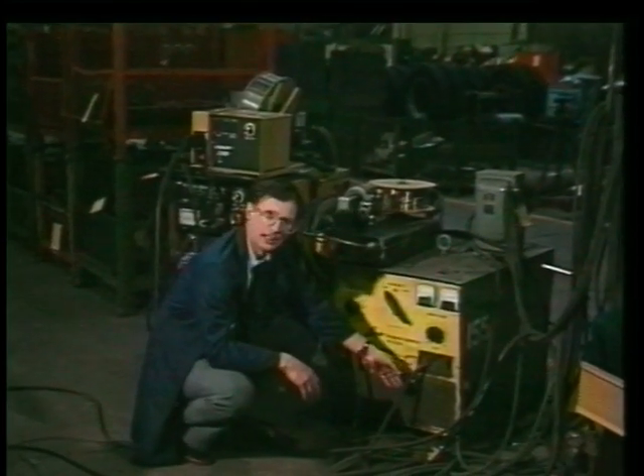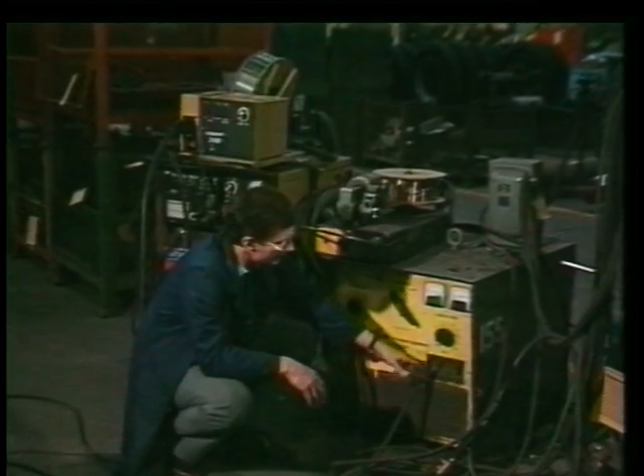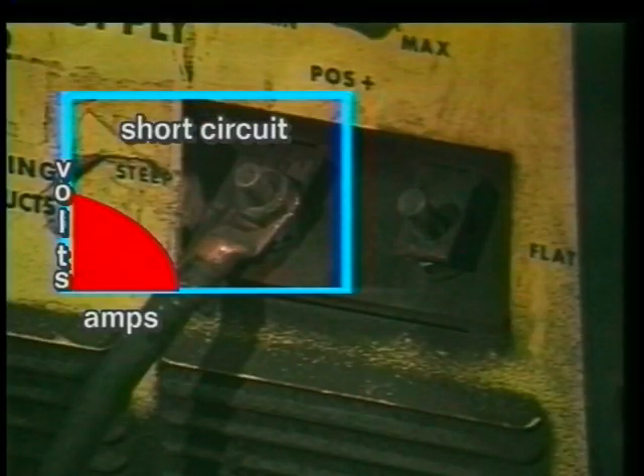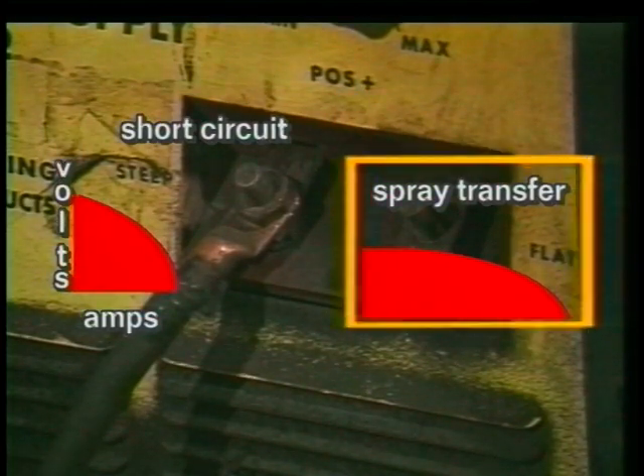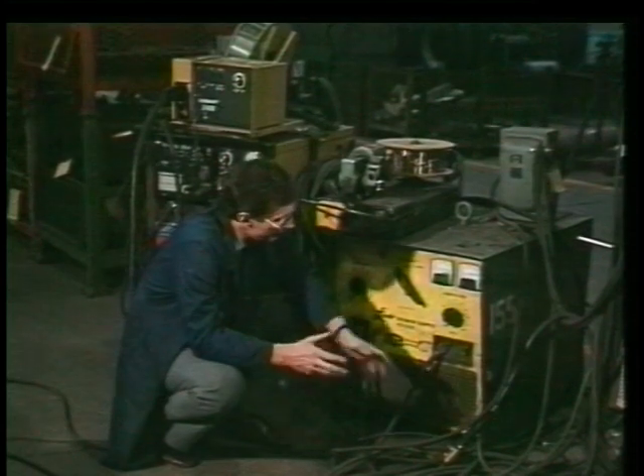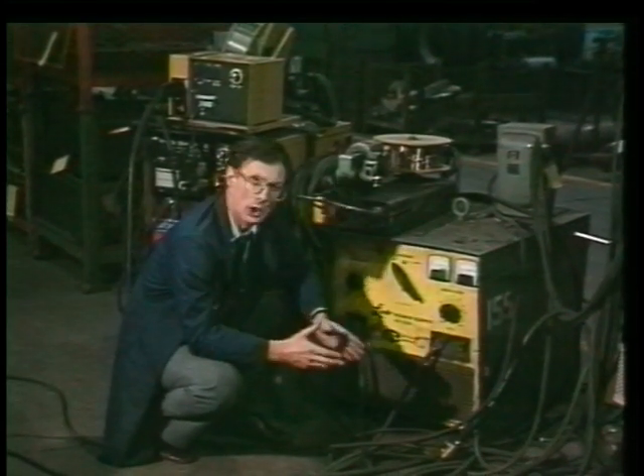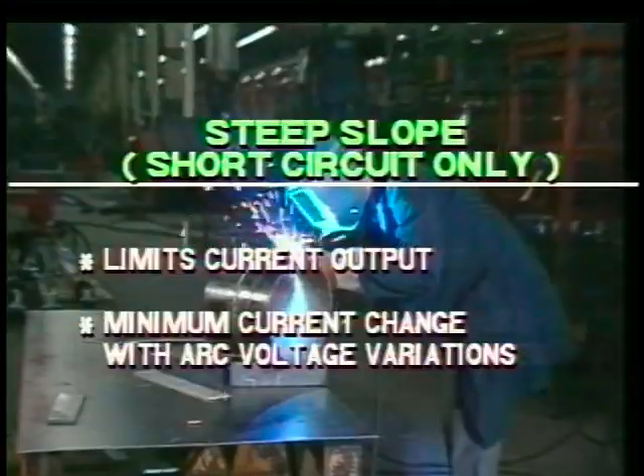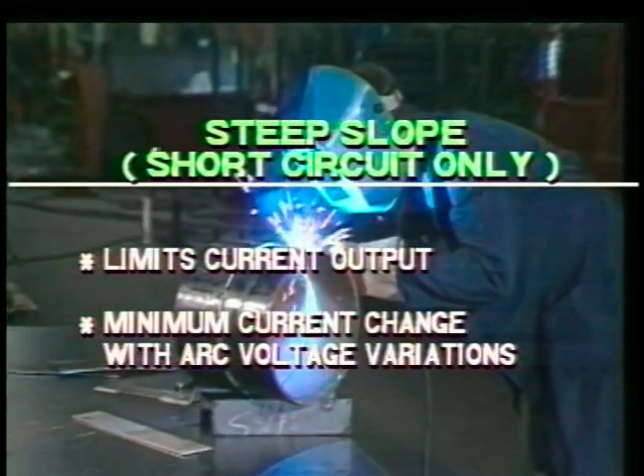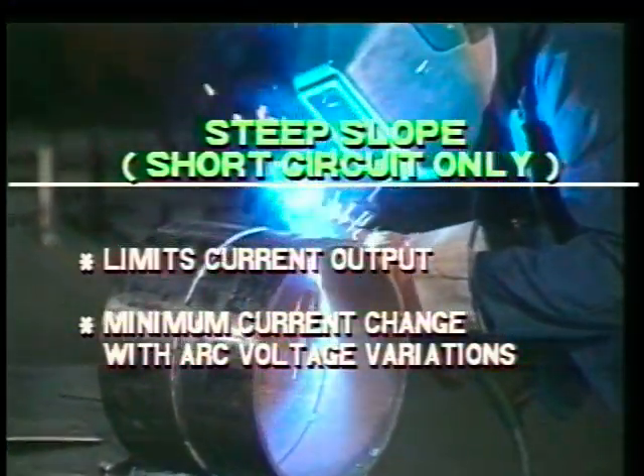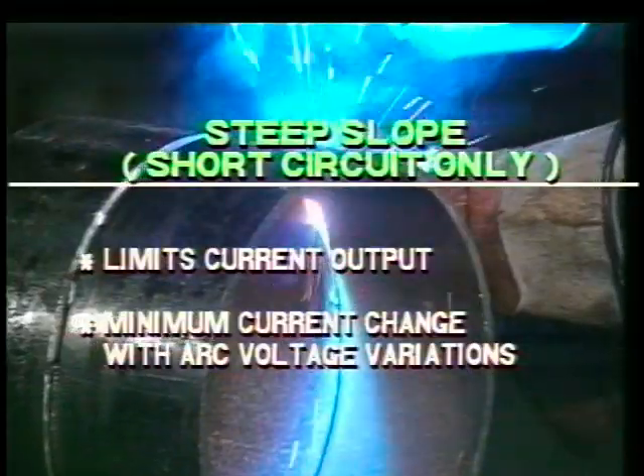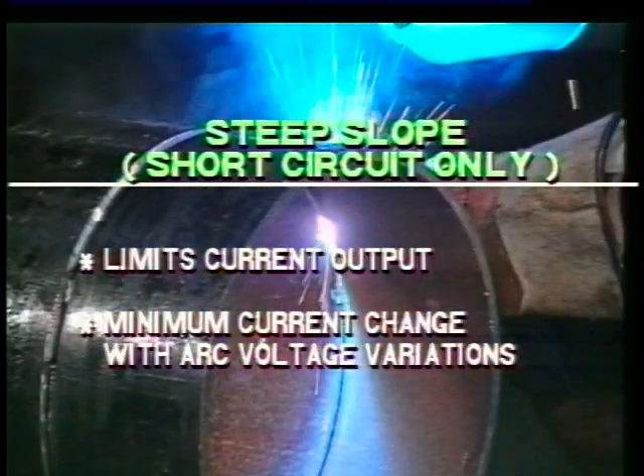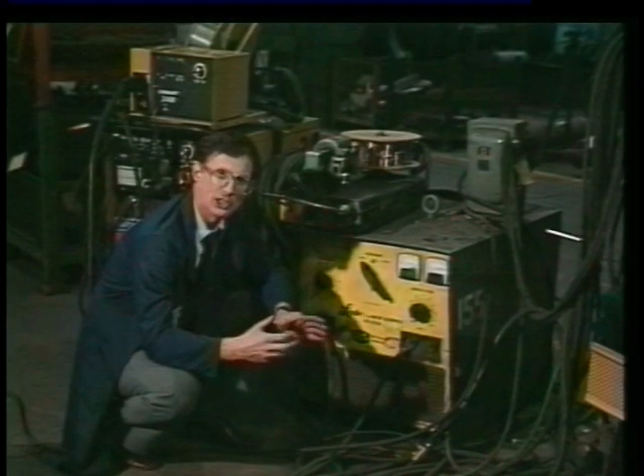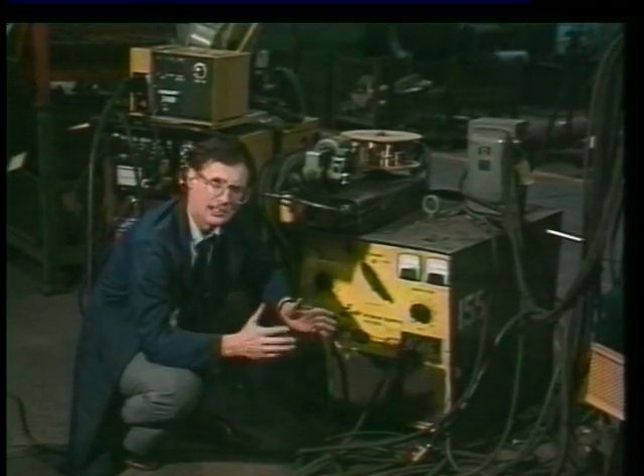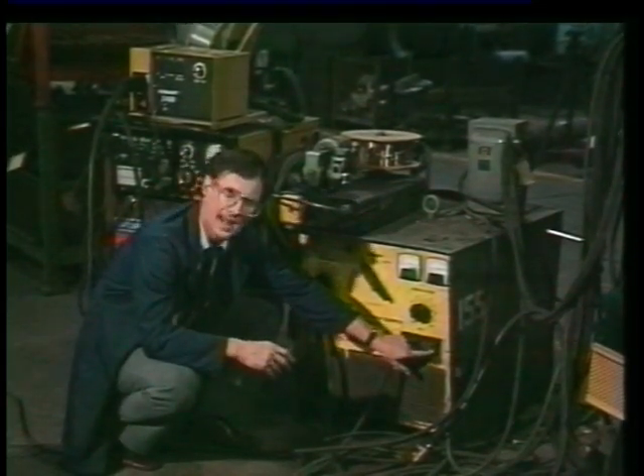Some of the units on the market offer two slope outputs, a steep slope and a flat slope. What does slope mean exactly? Well, in this particular machine, the steep slope provides control during the short circuit. It doesn't allow the current to be too high each time the wire short circuits. So if you're welding thin metals, having a steep slope output provides a little bit better control. And then when you go to spray transfer, you might possibly want to weld 3/16 to half inch steel, then you would have the flat slope output.